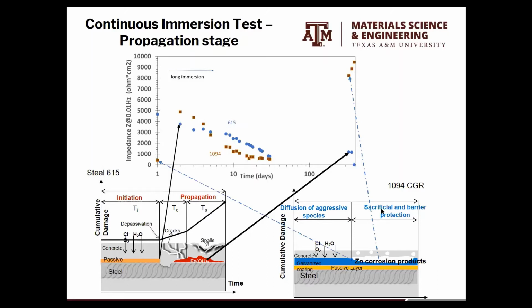Now what happened with this system, the 1094, which is a galvanized system. Remember, that's the layer, and we start at this point, the activation point, because we avoid this diffusion. What happens with this zinc layer? Well, you see the resistance of corrosion goes up but also goes down. Why? Because the zinc is sacrificing, dissolving at a higher rate than the steel. That is good because it's protecting, all right? But it's dissolving with time.